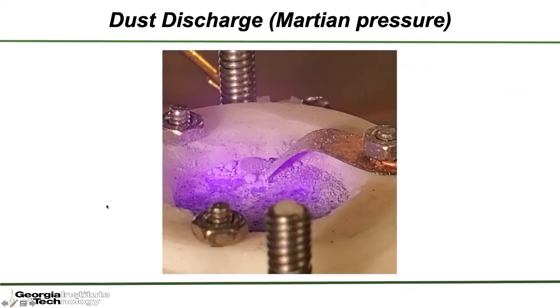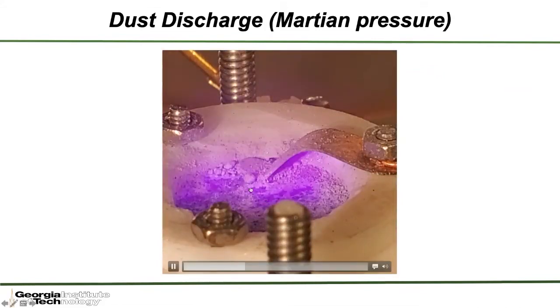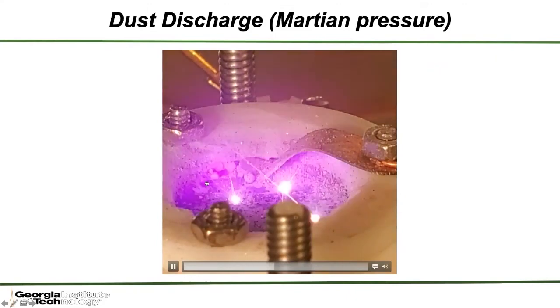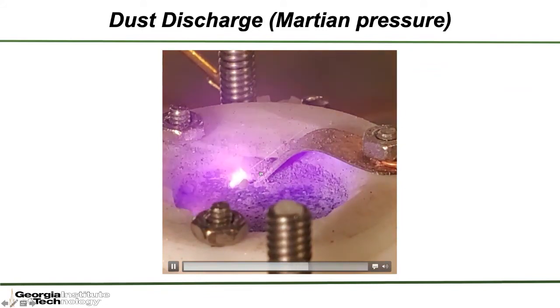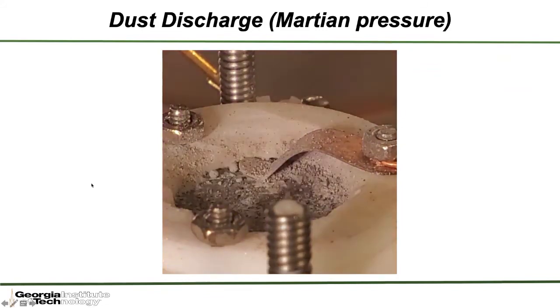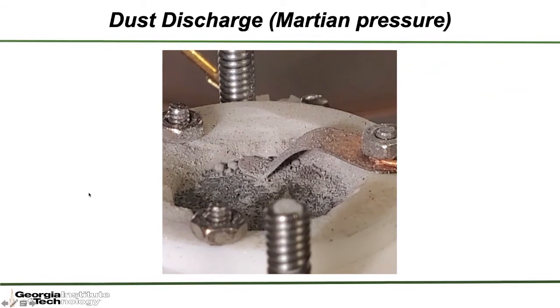And so right there, we see that we applied the potential to the surface, and what you get is this massive discharging and actually a plasma forming above that surface due to the large amount of electrostatic charging of those dust grains. And so you can see this is a really high potential. You wouldn't probably just apply this to a spacesuit. You'd have to do it in a much more controlled manner. But you really see that there's a lot of charging on these dust grains, and we can get them to interact strongly with these spacesuit materials.